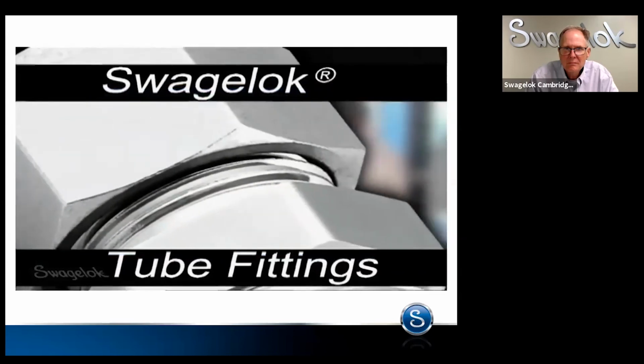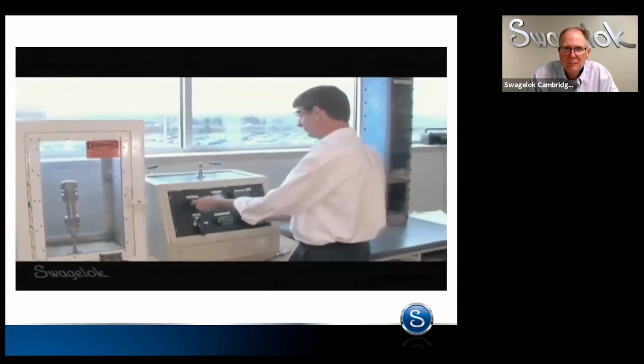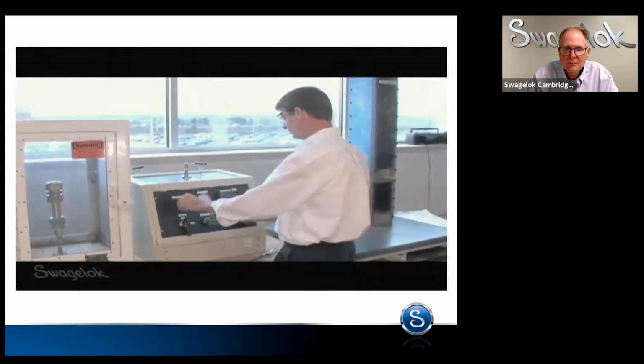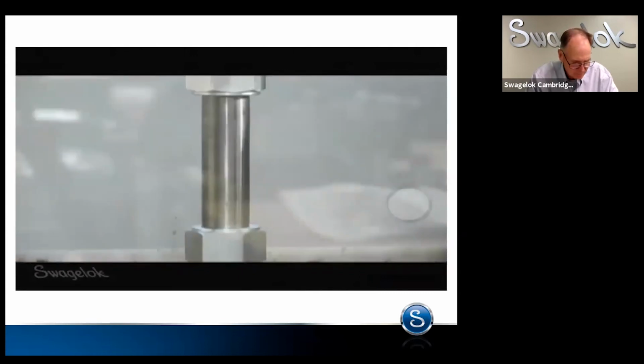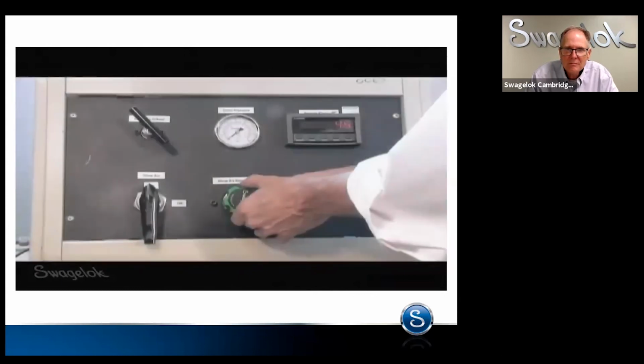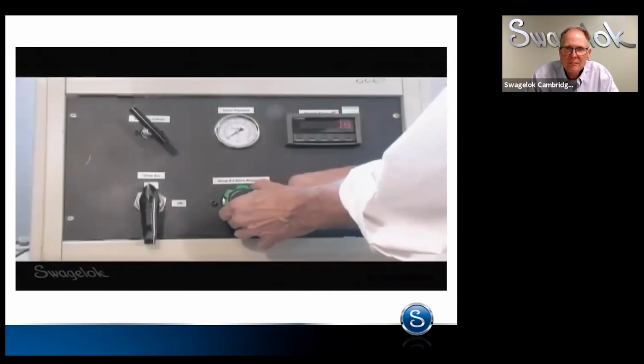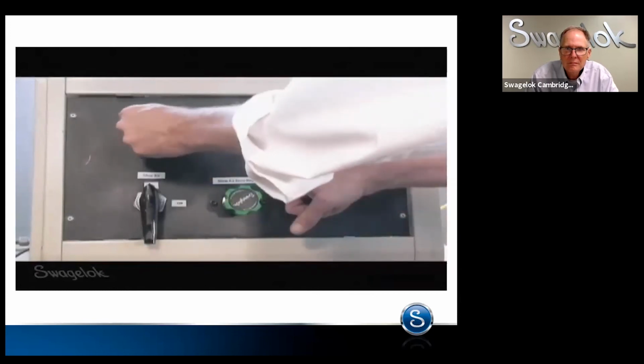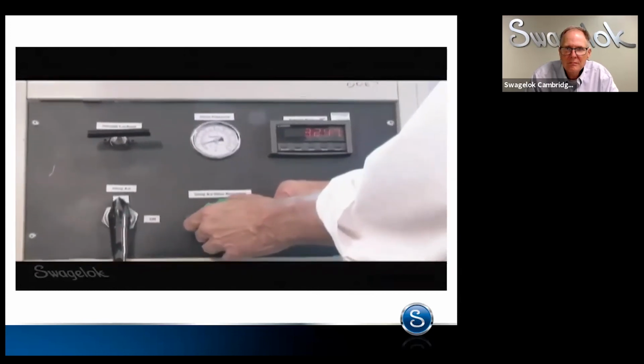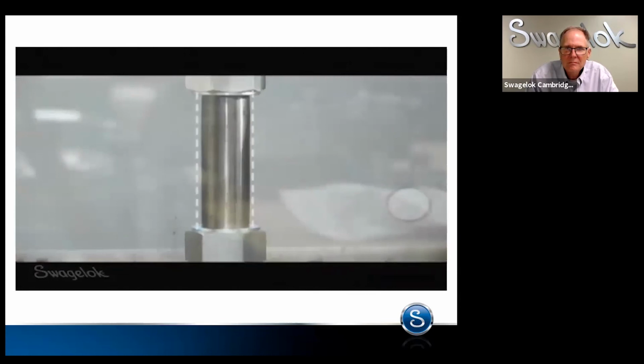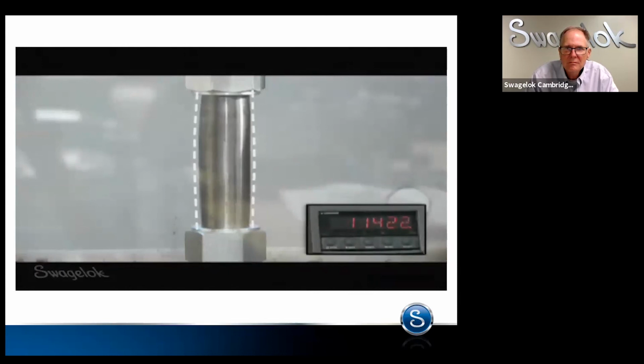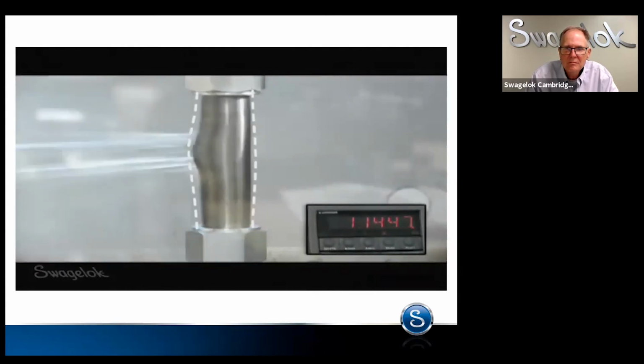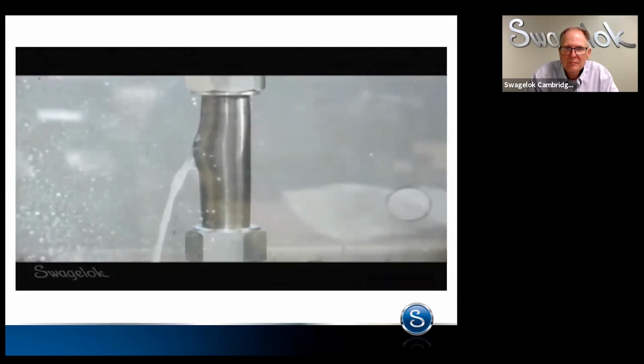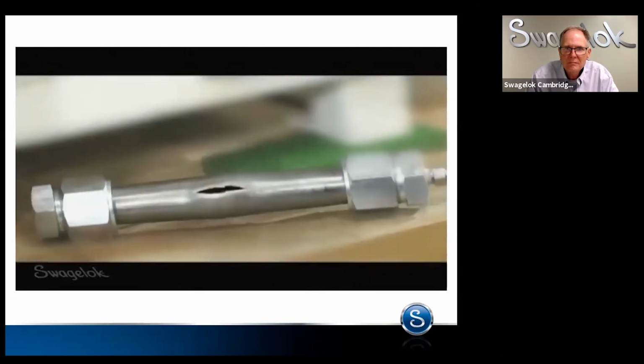tubing. One of the classic Swagelok tube fitting tests is the hydraulic burst test. Shown is a 1 1/4 inch tube assembled to a Swagelok tube fitting. The pressure is applied gradually until the allowable working pressure of the tubing, 3,200 psig, is reached. No leaks. The pressure is then increased in 1,000 psig increments until the tubing yields, and finally burst occurs, demonstrating the integrity of the Swagelok tube fitting.